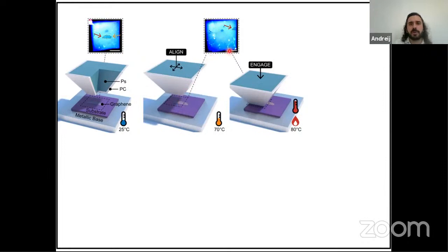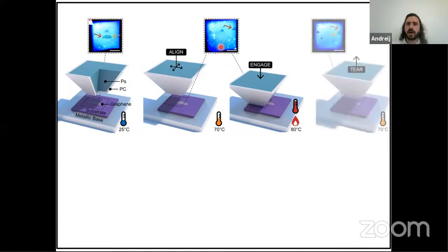So the next step is to align the pyramid edge to the middle of the graphene flake. This is just an optical picture showing this procedure. And then we engage, so we approach the pyramid stamp to the graphene sheet, and we do a temperature increase. And by doing that and cooling it back, we cut the half of the graphene sheet. So one of the graphene sheets is located at the pyramid stamp, and the remaining piece is located at the base, so at the substrate. So this is the trick.